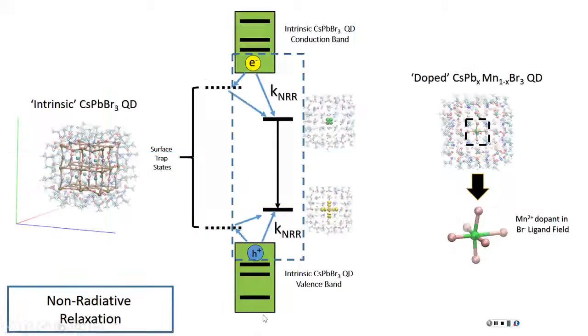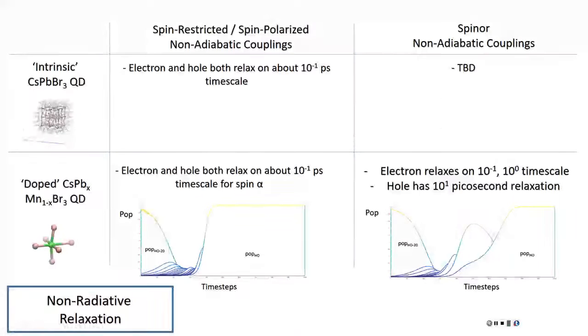I get what you're saying, but I don't have a good picture of it here. So basically, HOMO minus 1 and HOMO of the spin alpha are basically the same in energy. If you look at the DOS as the spinor, it's the same energy offset between the states. So it's not an energy issue. It's an orbital issue. You want to say that HOMO and HOMO minus 1 in spinors have primarily alpha character, so they're not contributed by beta. That's why it's going to be a spin flip. Yeah, that's why I didn't consider it anyway.